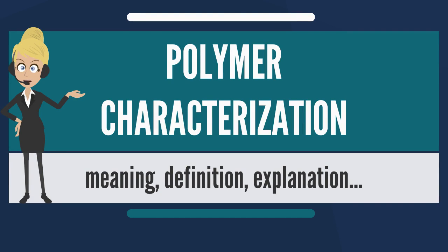Gel permeation chromatography, a type of size exclusion chromatography, is an especially useful technique used to directly determine the molecular weight distribution parameters based on the polymer's hydrodynamic volume. Gel permeation chromatography is often used in combination with multi-angle light scattering (MALS), low-angle laser light scattering (LALS), and/or viscometry for an absolute determination, that is, independent of the chromatographic separation details of the molecular weight distribution as well as the branching ratio and degree of long-chain branching of a polymer, provided a suitable solvent can be found.